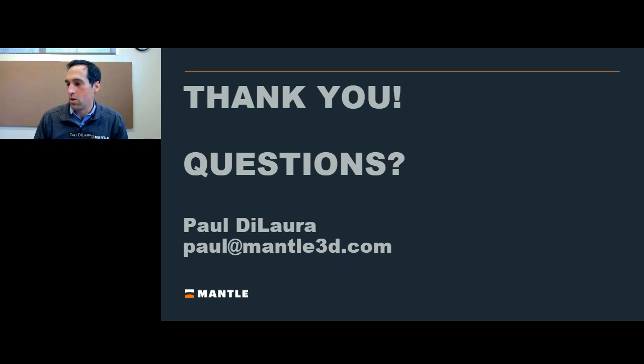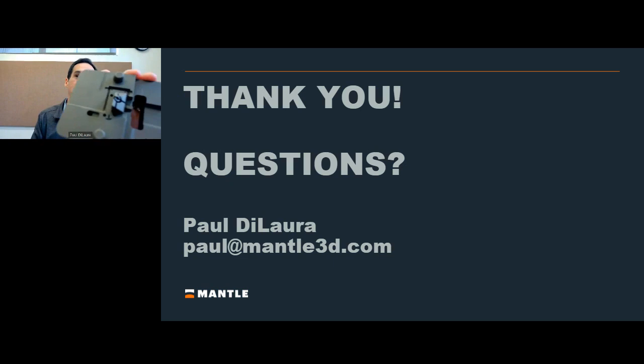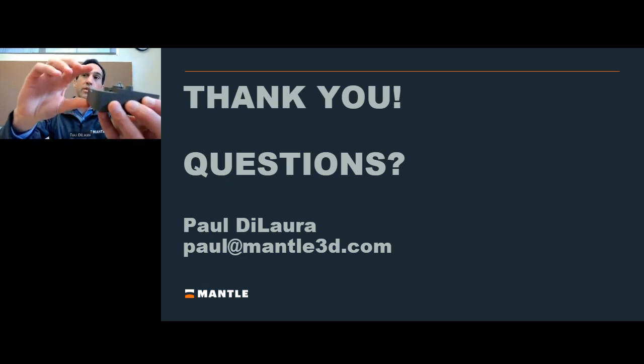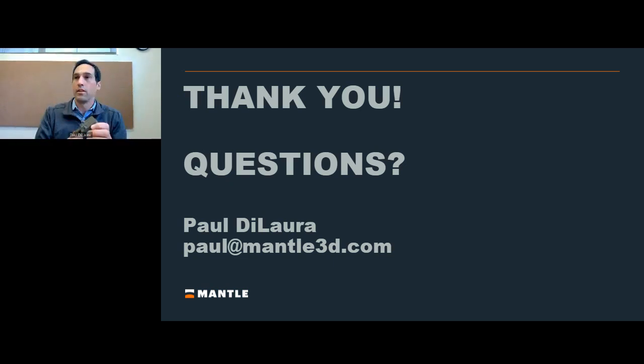Something that's relatively small, like this, you could print in less than a day. But if you're talking about something with a lot of feature detail, which takes a bit more time to machine, and also has some height to it, then you're talking on the order of days. An example with this particular project with Tessy Plastics: there were 2 components similar to this size, and then one smaller component that we could print all at once, and that was about 150 hours. Now that's a little bit on the longer side, but that was 3 components at once.